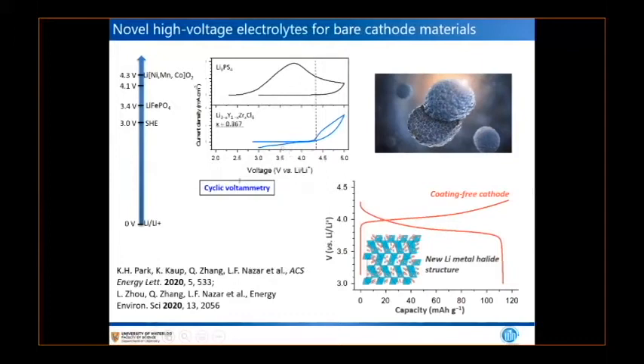And so the point is that if you use halides as opposed to the so-called sulfide materials, this is a cyclic voltammogram for anyone who's a scientist there, but the point is that we push this stability potential now into the window where the cathode material is at a commensurate voltage stability with the electrolyte. And so we have coating-free cathodes. We don't need to put any complicated passivating layers on these. And so these are these halide structures.